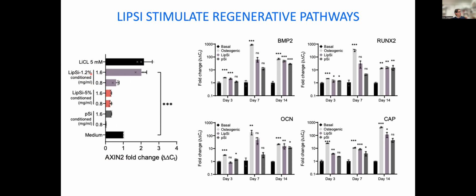We see that if we use 1.6 milligram per ml of particles, and we put them in contact with primary human periodontal stem cells, they do activate the Wnt beta-catenin pathway at the same level as they would if you were to stimulate them with lithium chloride. Porosilicon itself does not have any effect, nor does other formulation of lithiated silicon.